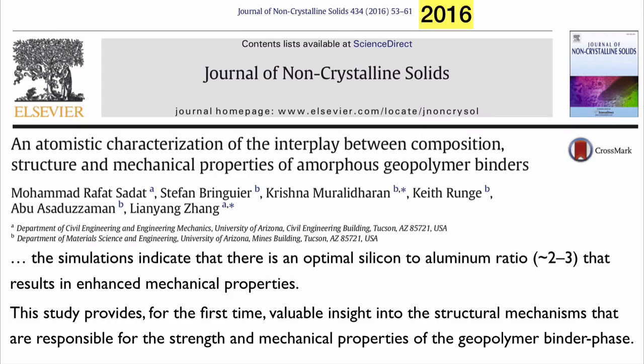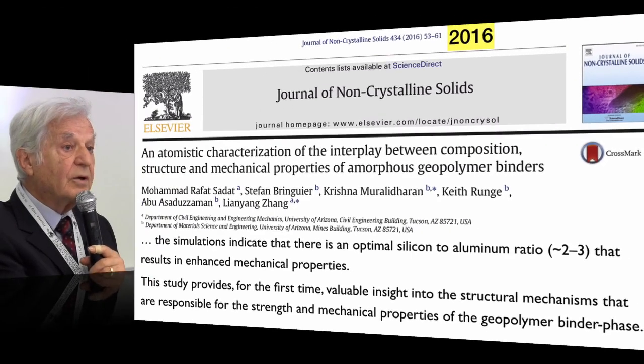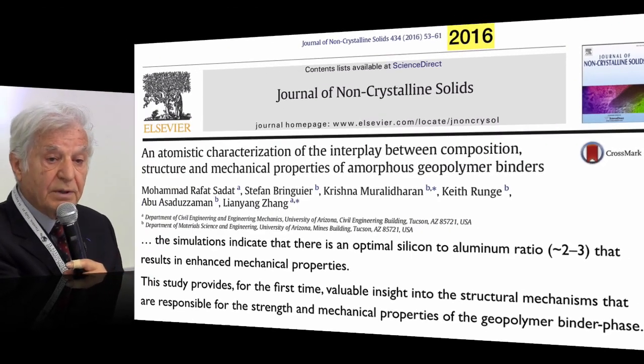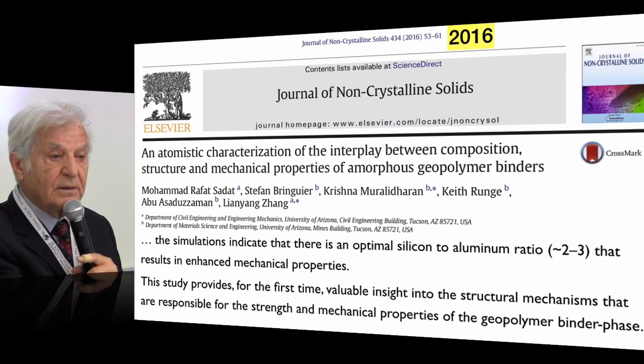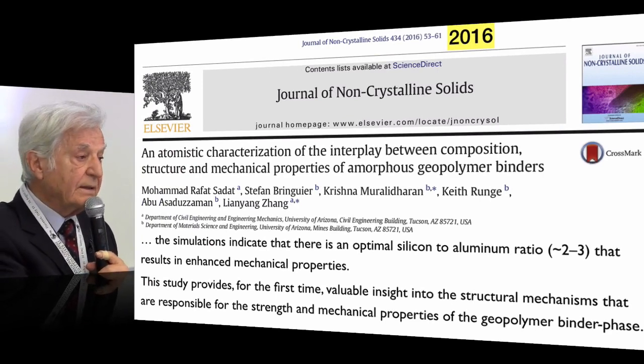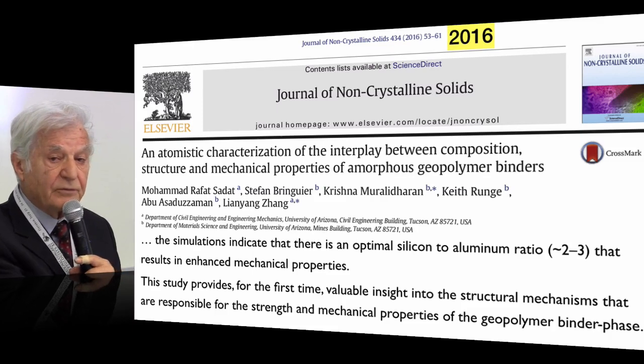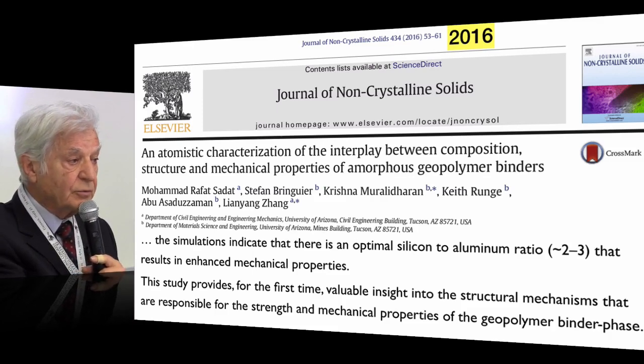The simulations show that it is the ratio 2 to 3 that is the best, that results in enhanced mechanical properties. This study provides for the first time valuable insight into the structural mechanism that are responsible for the strength and mechanical properties of the geopolymer binder phase. So now the computers are demonstrating that we were right when we stated that these are the ratio that we have to take in order to achieve good qualities.